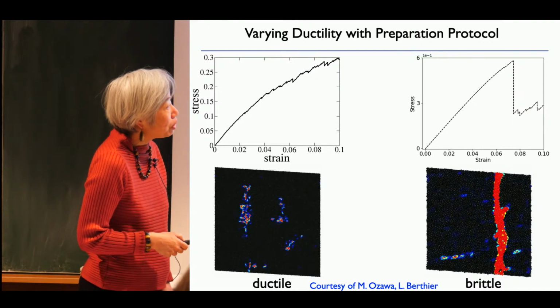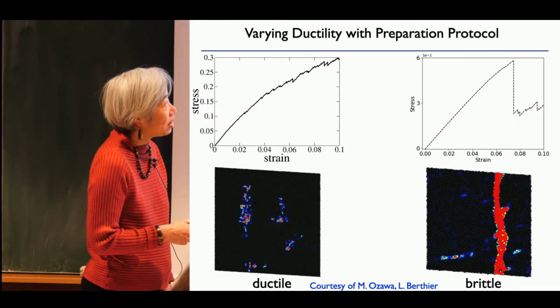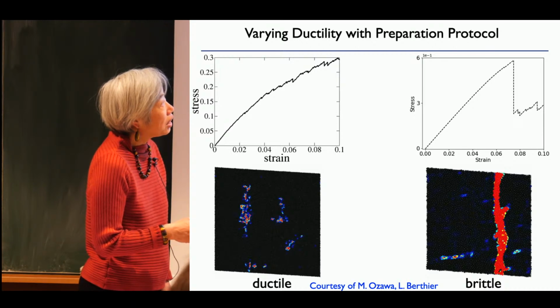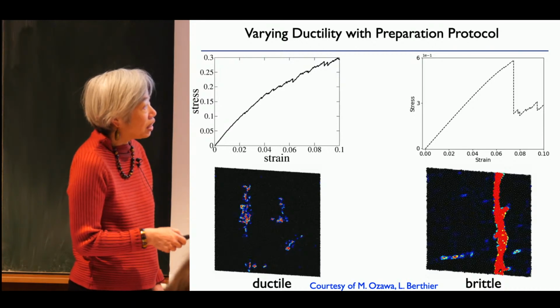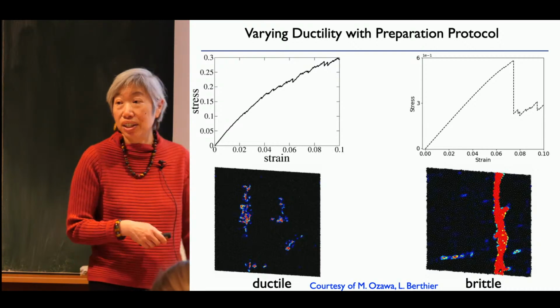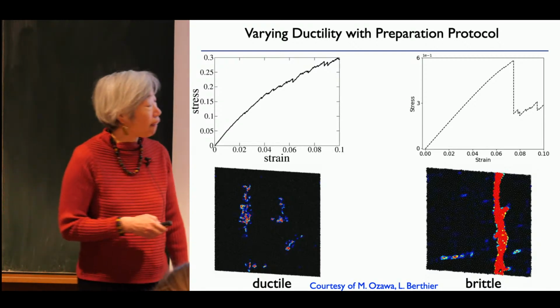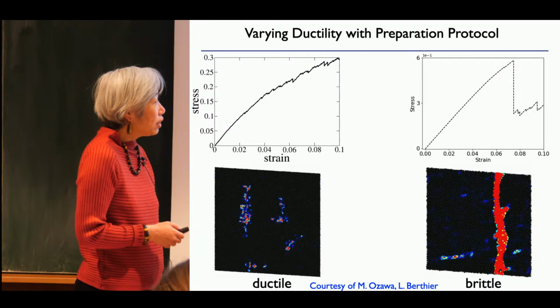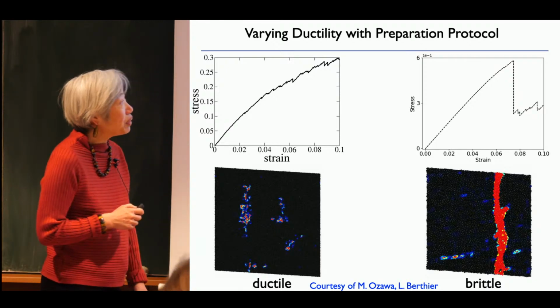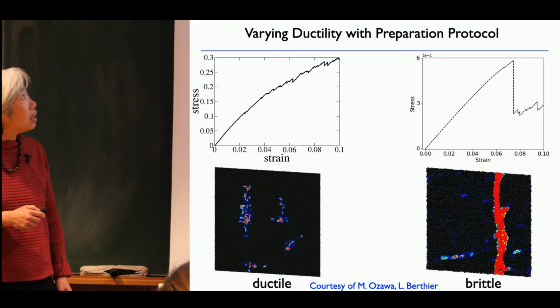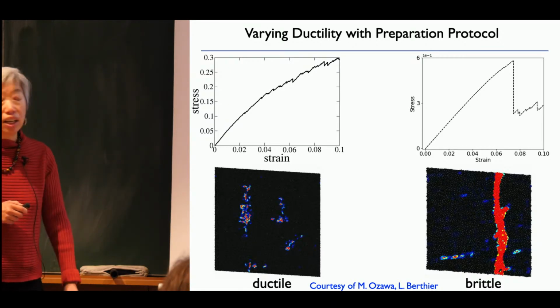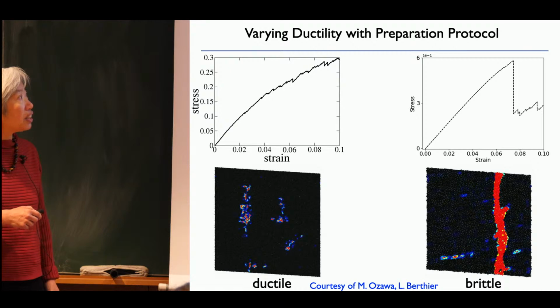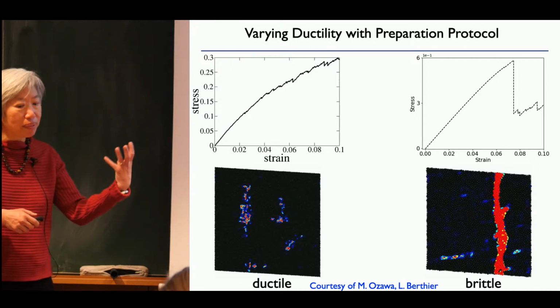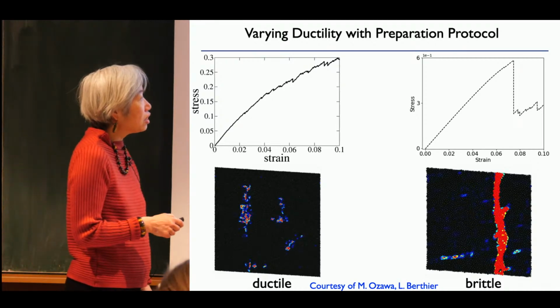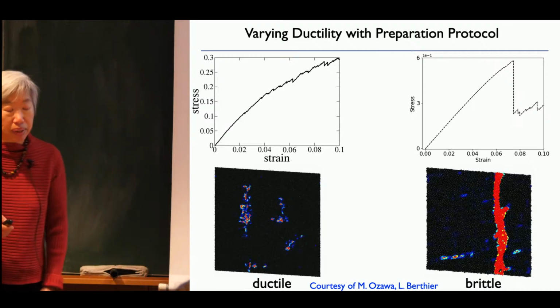And this is for the ductile case, though. For the brittle case, you see something very different. It starts out elastically, but then you see this very large stress drop, and that signals the formation of this shear band. So that's brittle behavior. First I'm going to talk about different ways of adjusting this ductility, but we would like to understand what are the microscopic factors, the microscopic physics that controls ductile versus brittle behavior.